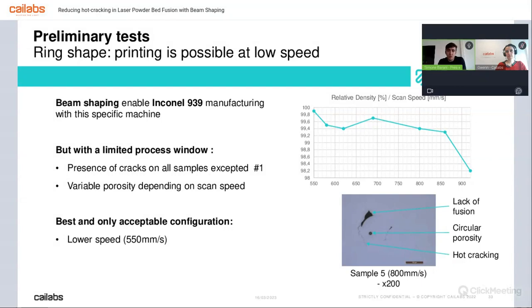So in general, we have printed some specimens changing the scan speed. And you can see in the graph on the right that as the scan speed for the ring shaper goes up, the density decreases. And what we have observed in following metallographic analysis is the three main defects that you can observe due to the additive manufacturing process, where you can observe a lack of fusion. That is the biggest porosity. Basically, it's empty material due to the fact that you don't have a correct cohesion between powder or between different